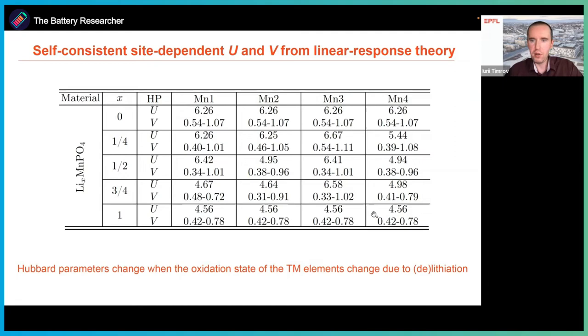And interestingly, in between these two limiting cases, the Hubbard parameter also changes. For example, when we add one lithium, so we have X equal 1/4, only one manganese shows a change in the Hubbard value. So manganese 4 went from 6.26 to 5.44, while all others remain more or less the same. They change slightly, but they remain more or less the same. When we're adding a second lithium, now the second manganese changed its Hubbard U value, and so on and so forth.